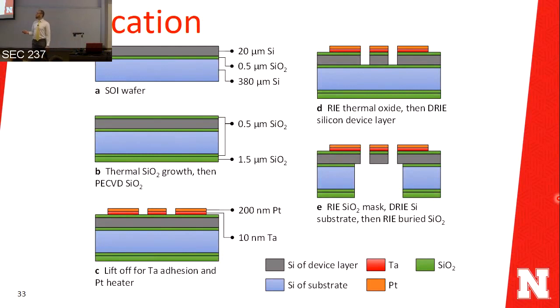The third step is to fabricate our heater. We fabricate the heater with electron beam evaporation followed by a liftoff process. Because platinum is a noble metal, it's hard to stick to most materials, so we have a tantalum adhesion layer of just 10 nanometers to promote the adhesion between the platinum and the silicon dioxide.